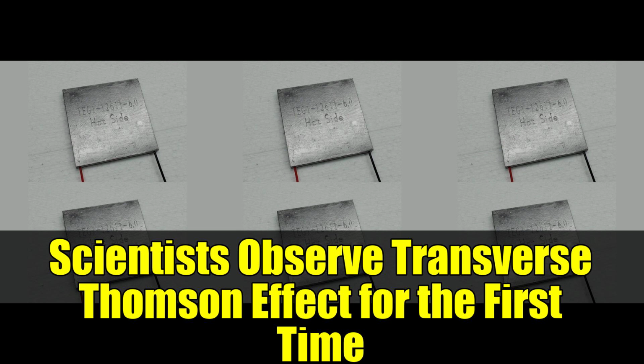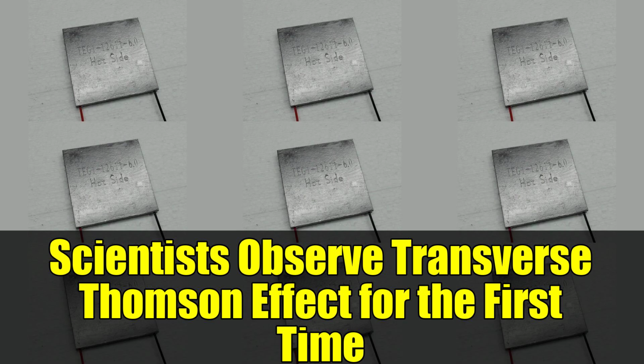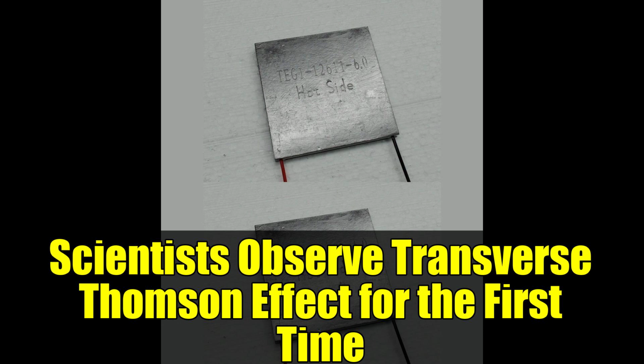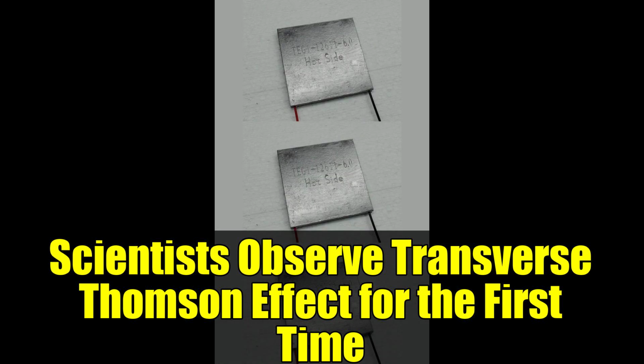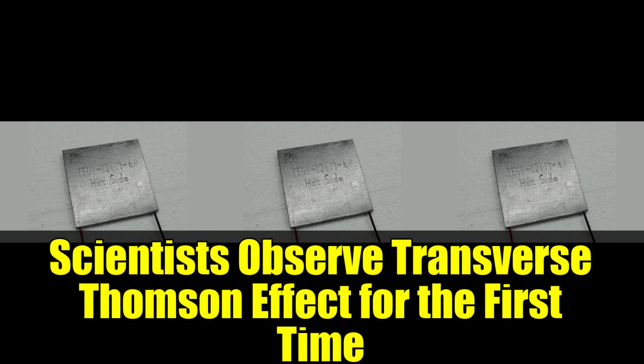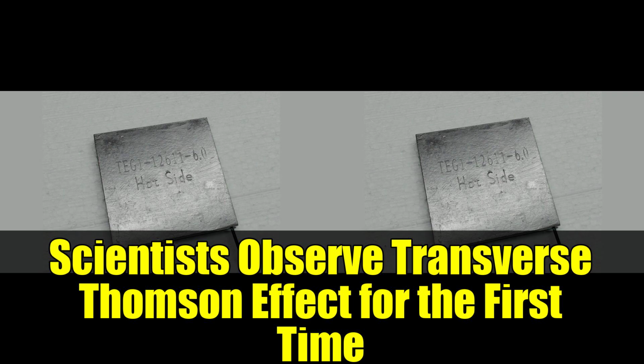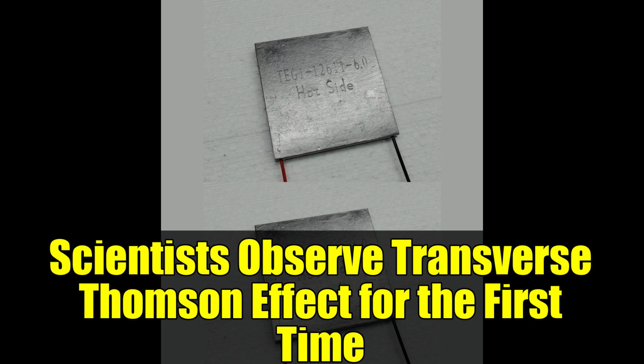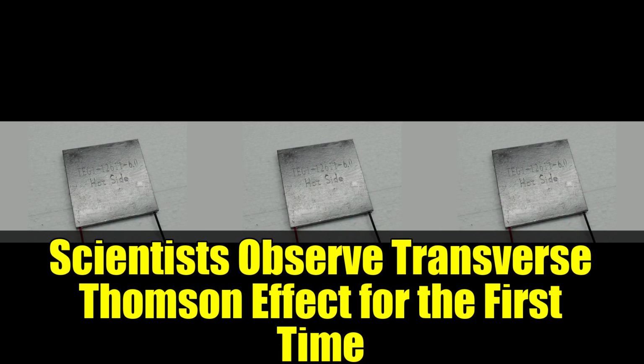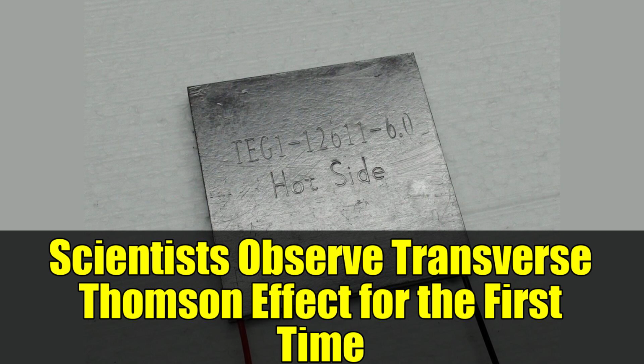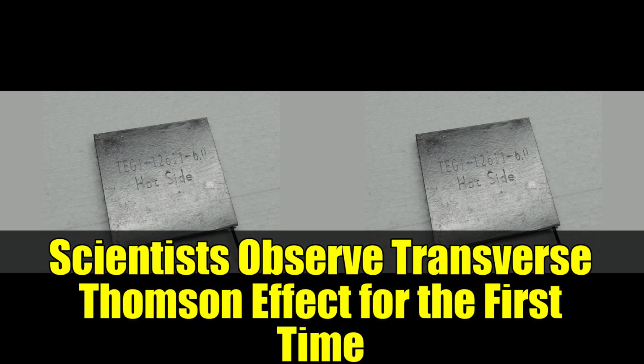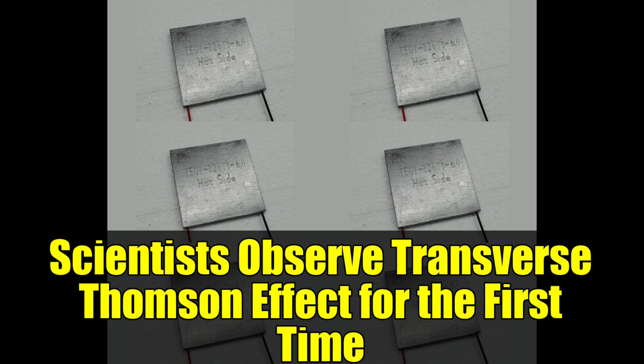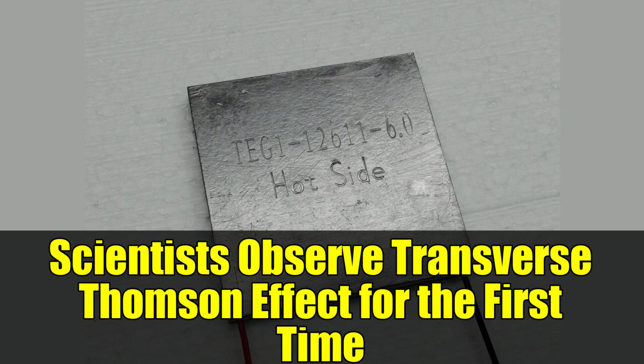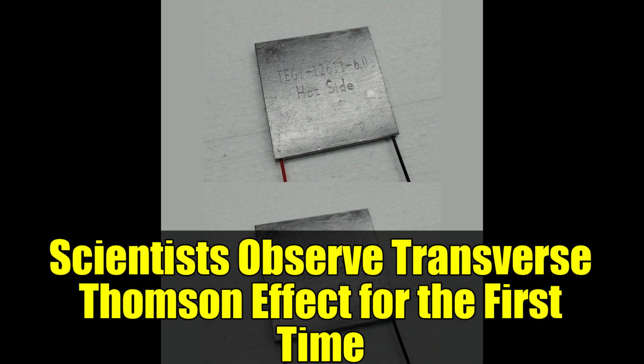The researchers discovered that the Transverse Thomson coefficient comprises two competing components, one related to the temperature derivative of the Nernst coefficient, generally causing heating, and another related to the Nernst coefficient magnitude, generally causing cooling. The competition between these components creates the field-dependent sign reversal observed in their experiments. Their numerical simulations accurately reproduced the experimental observations, confirming the theoretical understanding of the phenomenon and validating their measurement technique. The discovery opens new possibilities for thermal management technologies, particularly in applications requiring precise, localized heat control.